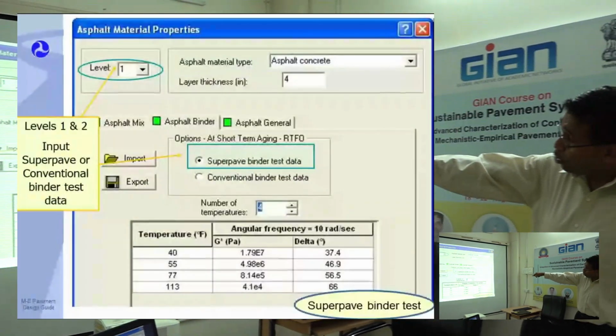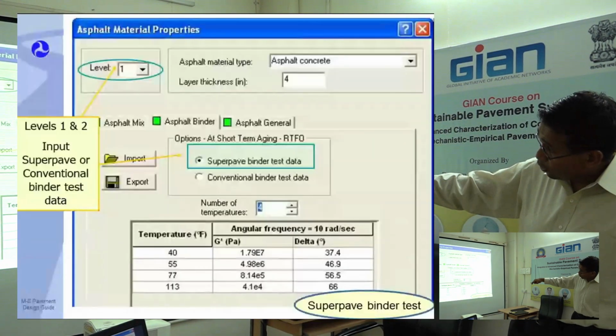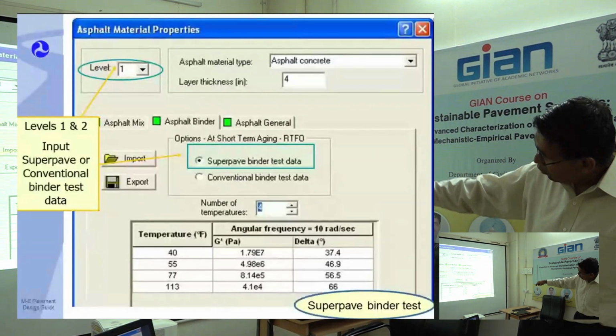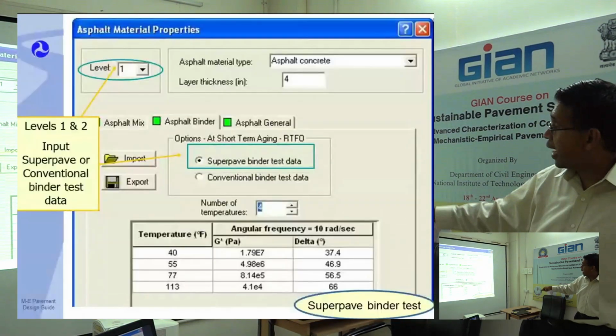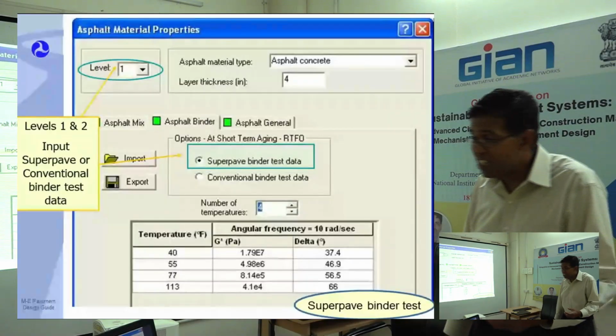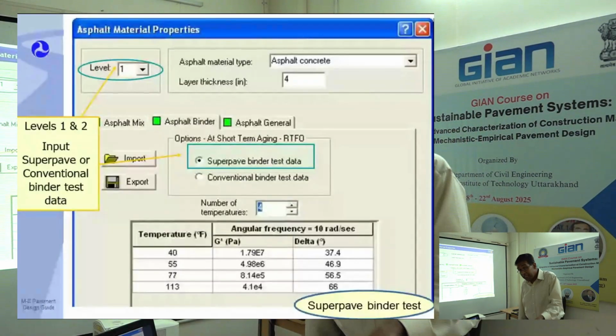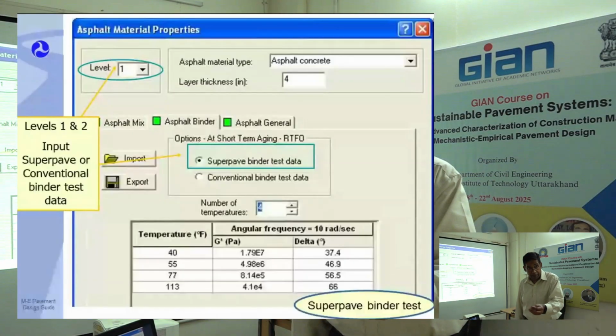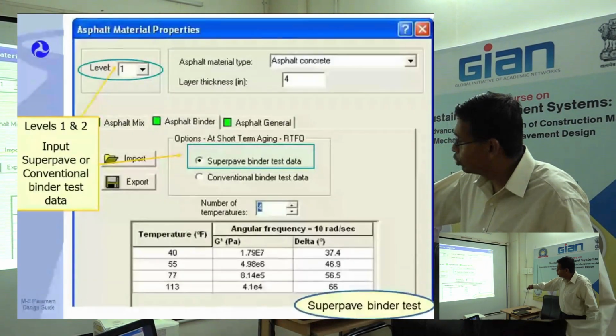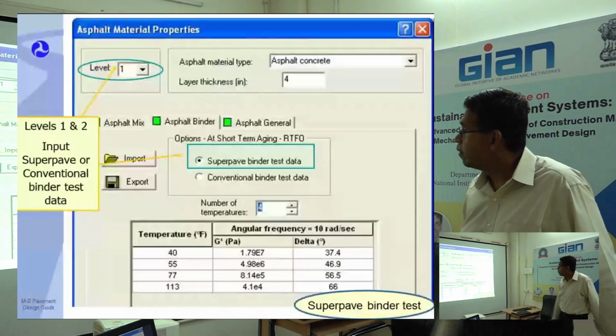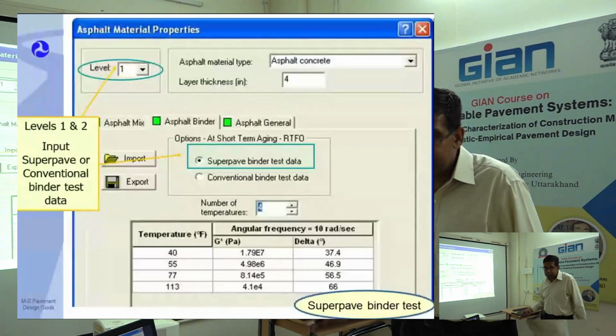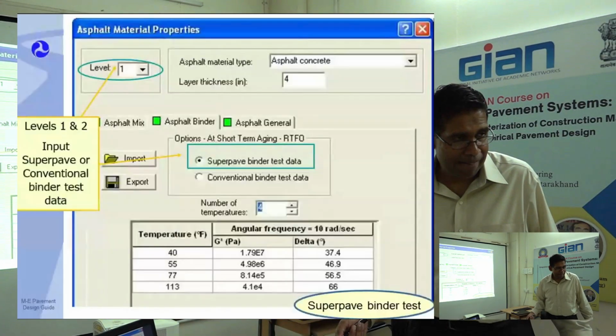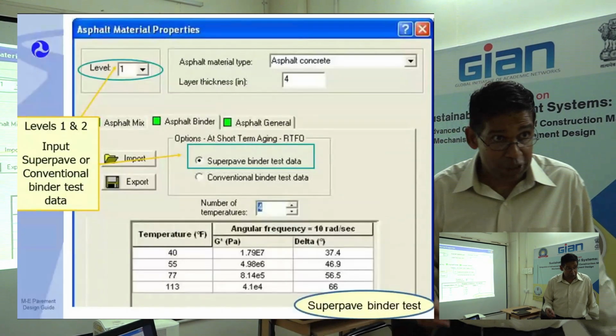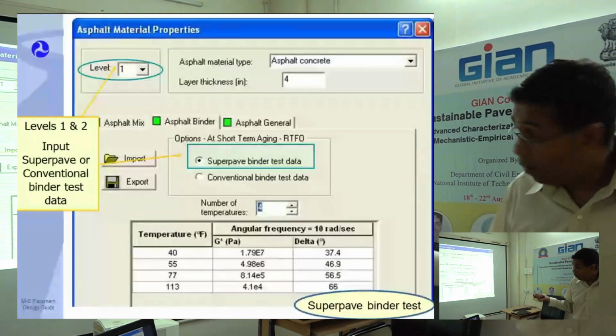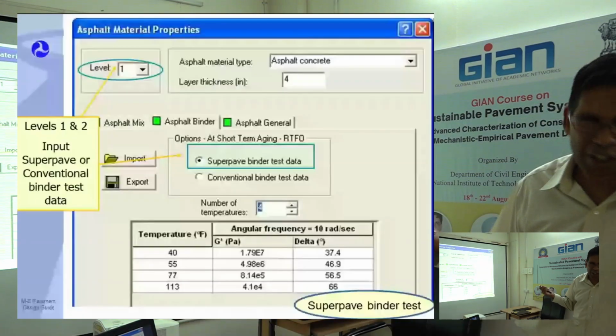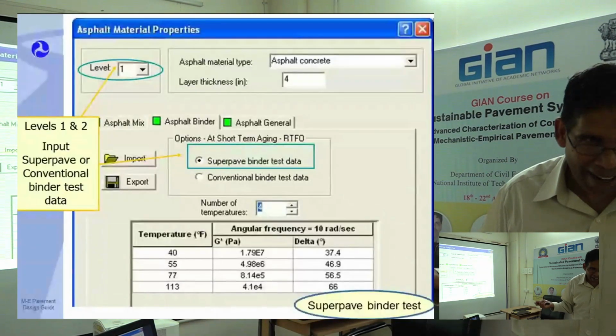Asphalt concrete, you can use superpave binder test. Different temperatures, 40, 55, 77, 113. And then you have different delta phase angle. Phase angle is elasticity. If the phase angle is 0, then it's completely elastic. Phase angle of 90 is completely plastic. And of course, asphalt binder is closer to 90, so it's not elastic. Right? Asphalt concrete is more elastic than asphalt binder. Why? Asphalt concrete, hot mix asphalt is more elastic. If I got the phase angle of hot mix asphalt, it will be around 45, 50 phase angle.